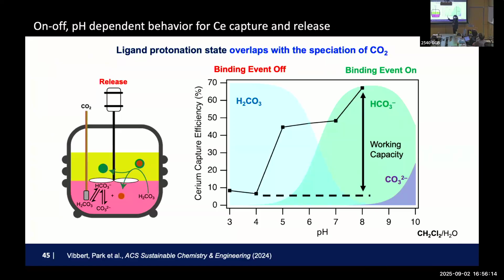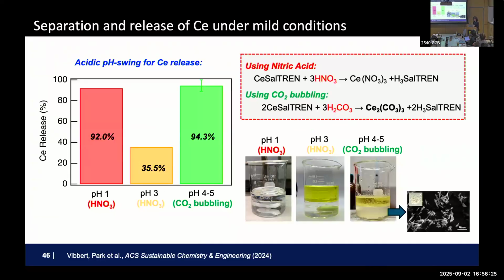And then we just need to bubble air to degas all the CO2, get a more neutral pH, then we were able to restructure all the structural ligand. So let's test that, and then this is the data. So this is pH 1. This is typically what conventional mining people do. So put pH 1 or even lower, strong acid on the system, then you crash out all the metal, recover 92 plus whatever percent.